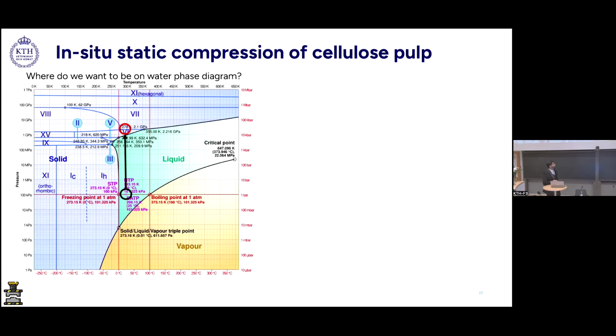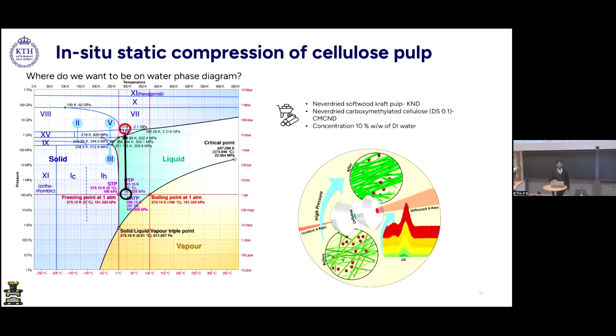The material that we will be using is the same material as before, so never dried carboxymethylated pulp. Also, we have added the never dried kraft pulp in this setup. The experimental philosophy was we take a tiny amount of sample, we compress it between two diamonds, we shine the X-rays through them, and we see how the material is changing its structure while it's doing so.